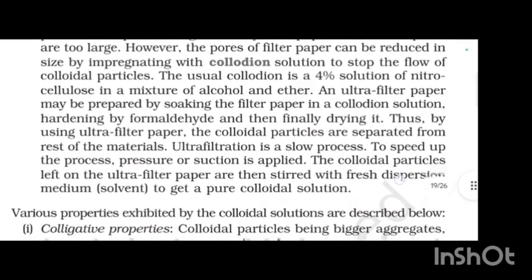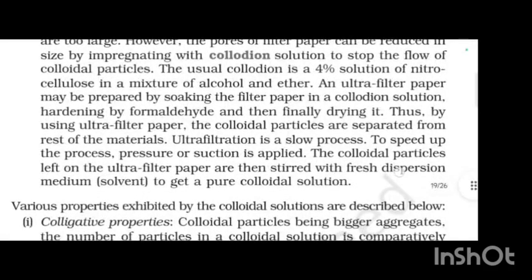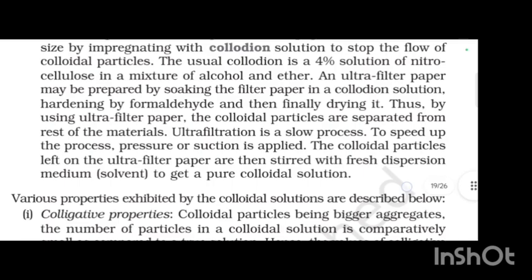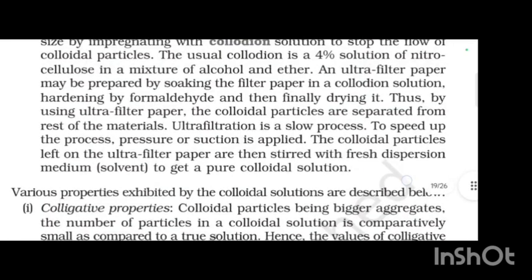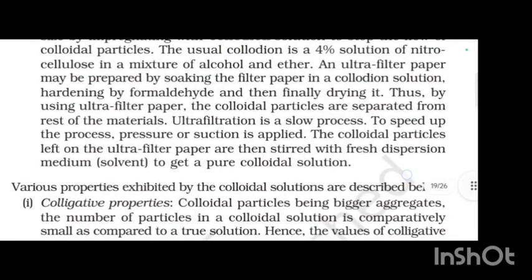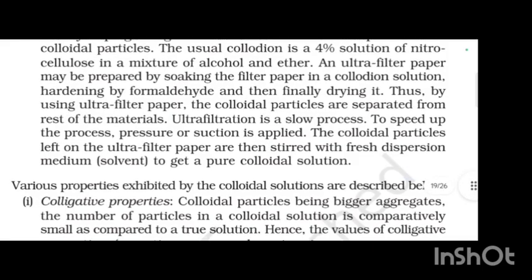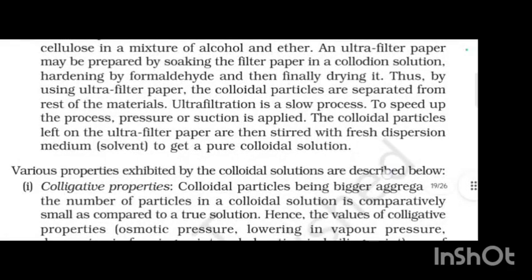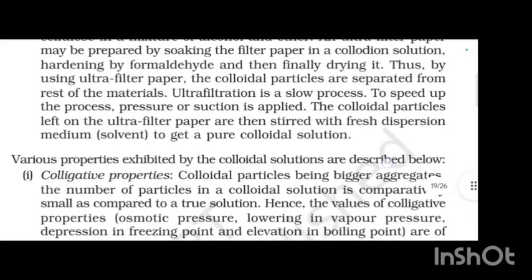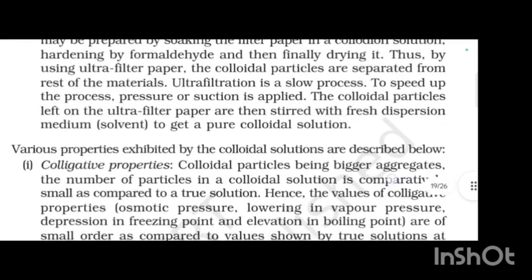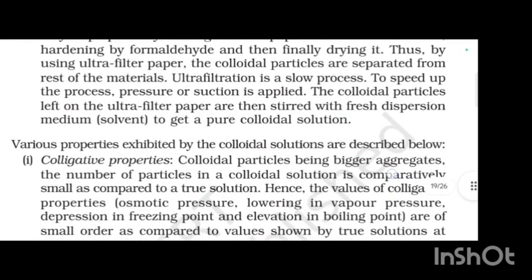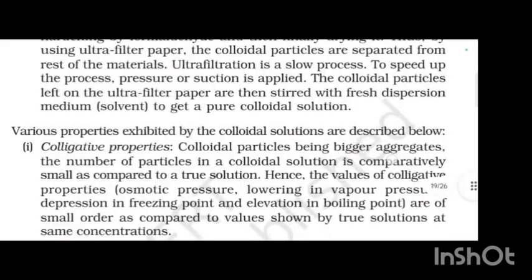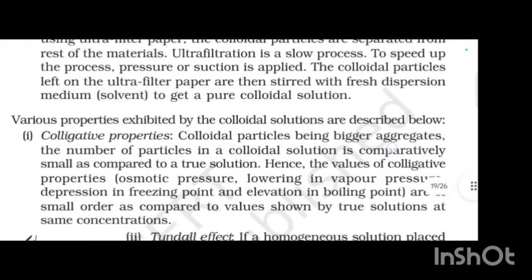However, the pores of filter paper can be reduced in size by impregnating with collodion solution to stop the flow of colloidal particles. The usual collodion is a 4% solution of nitrocellulose in a mixture of alcohol and ether. An ultrafilter paper may be prepared by soaking the filter paper in a collodion solution, hardening by formaldehyde, and then finally drying it. Thus, by using ultrafilter paper, the colloidal particles are separated from the rest of the materials.